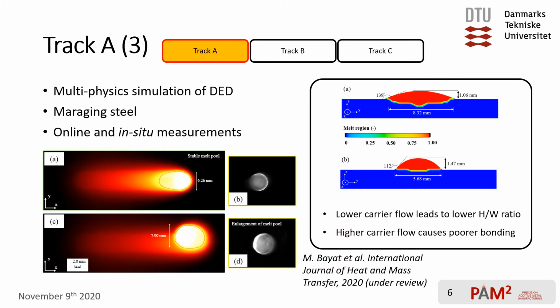And in the final part of the first investigation track, I developed a multi-physics simulation of the DED process of maraging steel, where I compared my numerical predictions with ex situ and also in situ measurements using a thermal camera. We also found that by using higher carrier flow speeds, we will have a weaker bonding between the track and also the base plate.